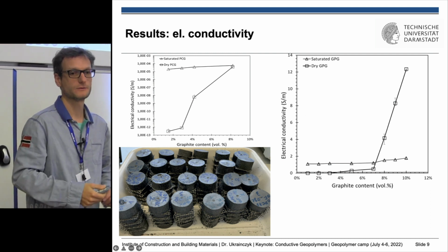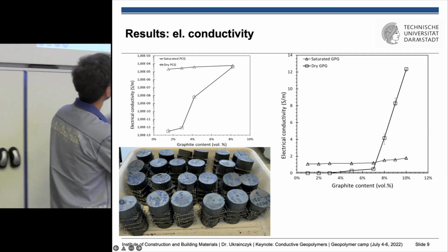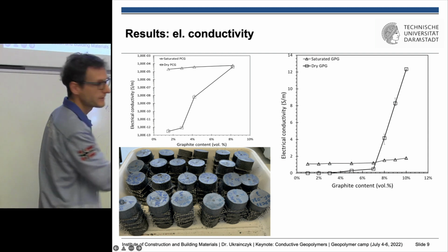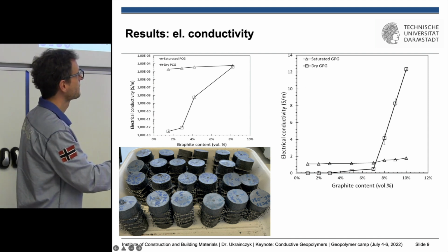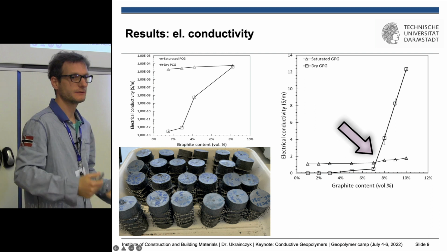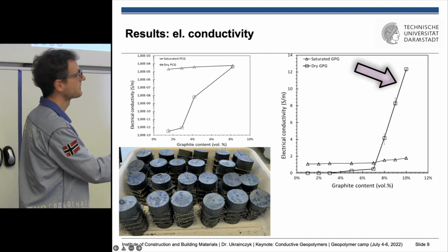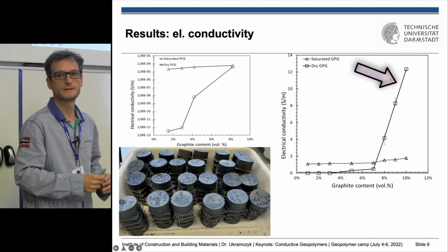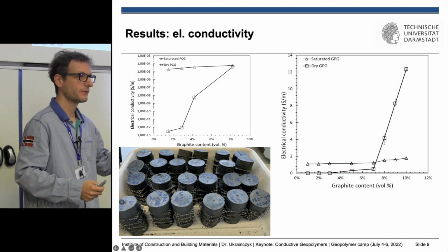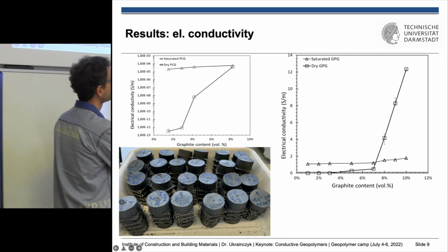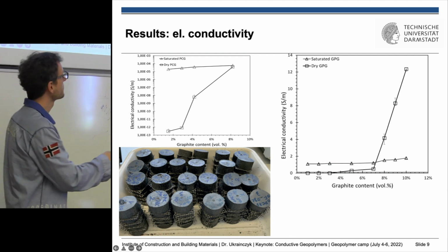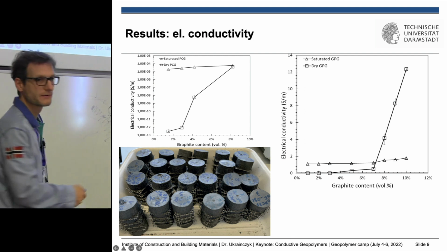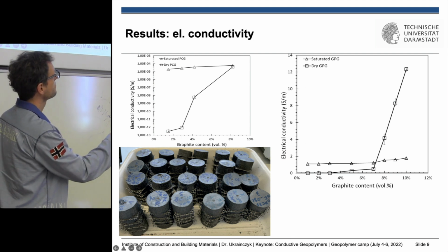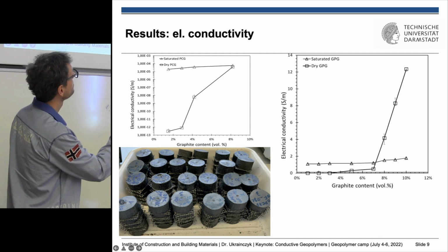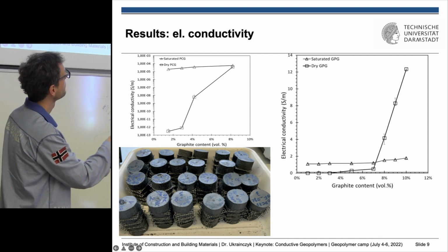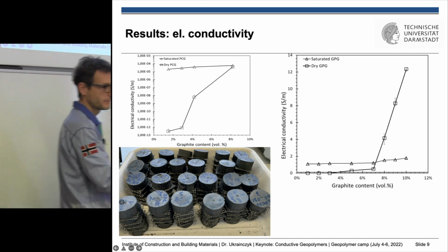So this is practically not conductive, and I would also mention that this conductivity is actually probably mainly from the ionic conductivity. And here we can see, when we compare the dry and the saturated, that there is a certain percolation threshold, or conductivity threshold, when the graphite starts to be connected, and when it's connected, the current can flow through the connected particles of the graphite. So above some 7%, it's working. It starts to percolate. And interestingly, actually for the dry, so this is for the saturated, water saturated, or with the pore solution.